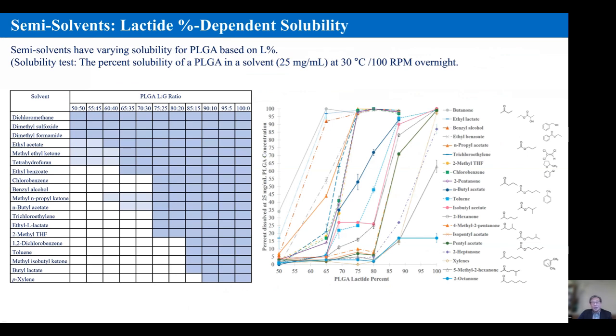PLGA ranges in LG ratio from 50-50 all the way to 100. They have the same name, PLGA, but they are not exactly the same polymers. Now, the left table and the right side figure are exactly the same information, but it's easier to explain using the table here. For example, let's talk about benzyl alcohol. Benzyl alcohol, the white area means it doesn't dissolve. Benzyl alcohol does not dissolve PLGA 50-50 all the way up to 70-30. But for PLGA LG ratio 75-25, benzyl alcohol dissolves.